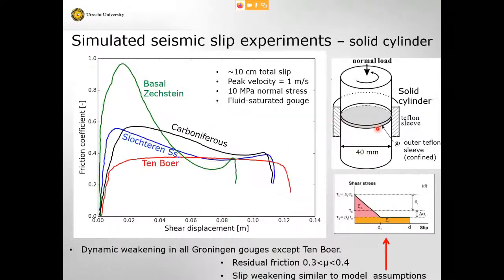We found this kind of thing. We have a cylinder here with the crushed up rock in between. We load it, and then we subject it to this very fast pulse going right up to 1 meter per second and down again, in a displacement of about 10 or 20, in this case 12 centimeters here. A displacement pulse of just 12 centimeters in a fraction of a second. So it's a simulated earthquake, and what we found was this anhydrite carbonate rock on top of the reservoir, the top of the sequence, extremely strong, shows an enormous drop in strength.